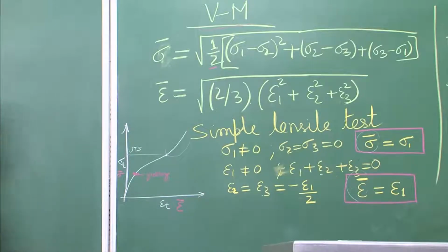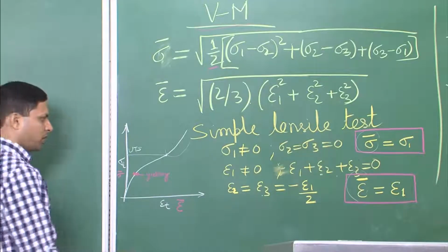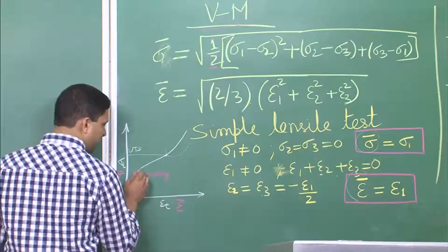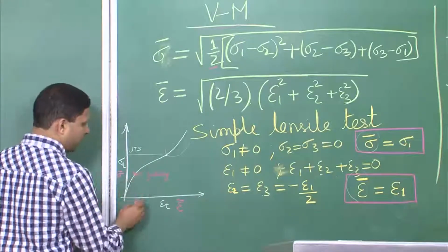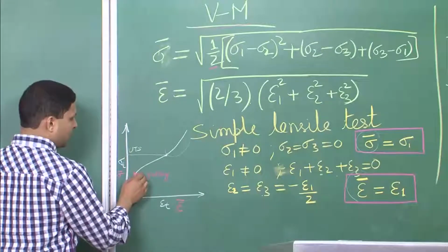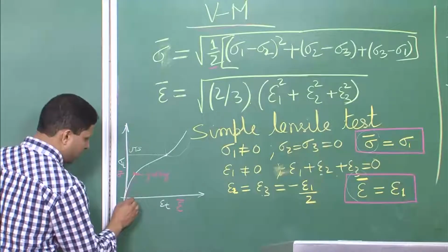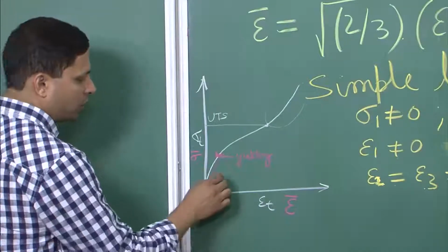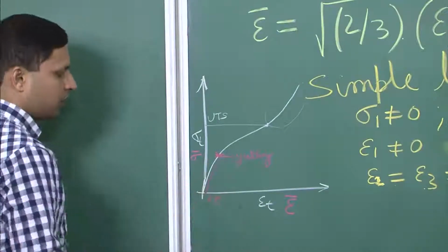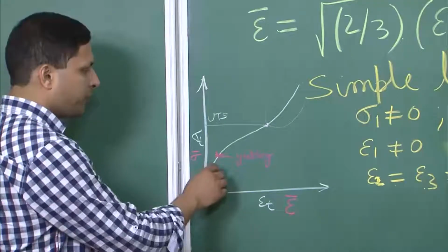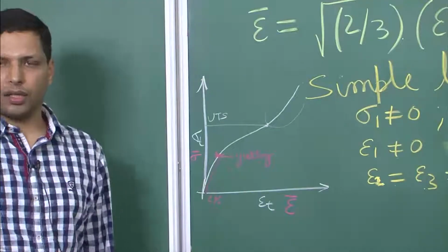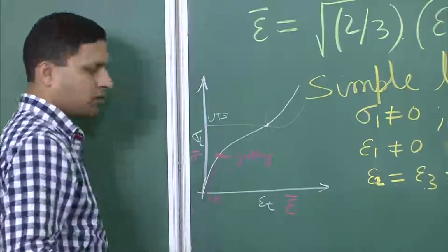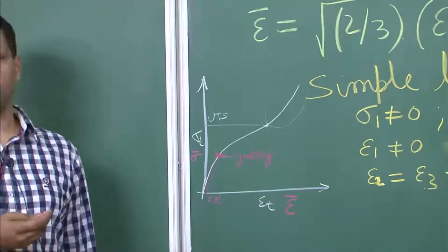You may not have thought about it so much in depth earlier, but now look at it and realize that at this point, at this whatever strain, if you look at it over here, it is 0.2%. So beyond this 0.2% or whatever strain, once the material has started deforming plastically, you still need to increase the stress.